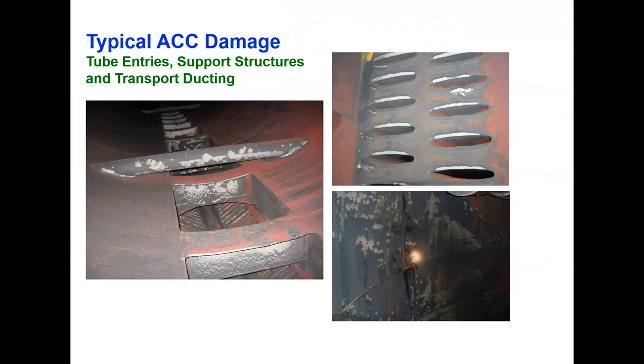And so this is the typical damage that we're going to be talking about. Basically, at the tube entries, as you can see here in the upper ducts, and here, and on the cross support members here and here. And then in the transport ducting from the steam turbine. And basically, the more white areas there are, and the worse the white areas are, the worse is the damage, and the greater is the corrosion. And of course, that means the higher is the transport of iron into the main part of the plant.